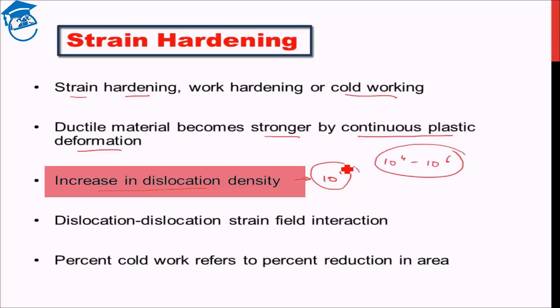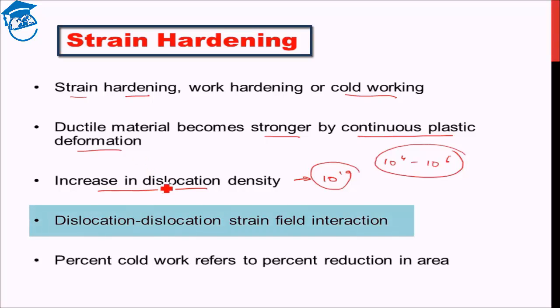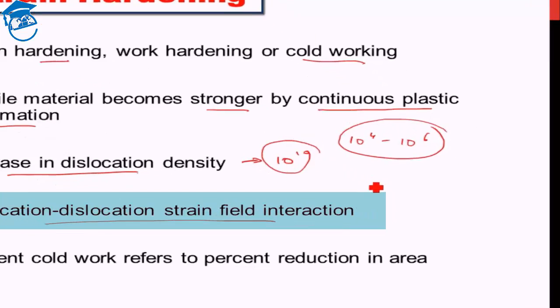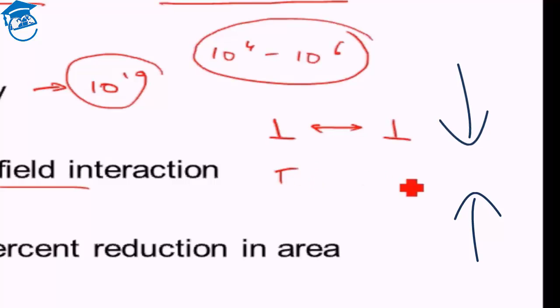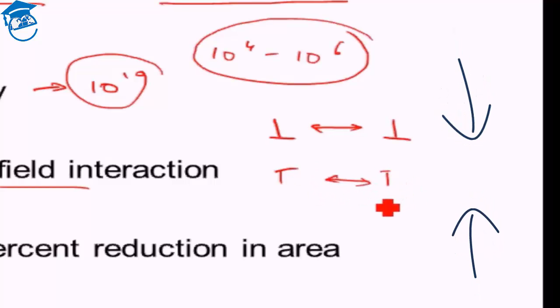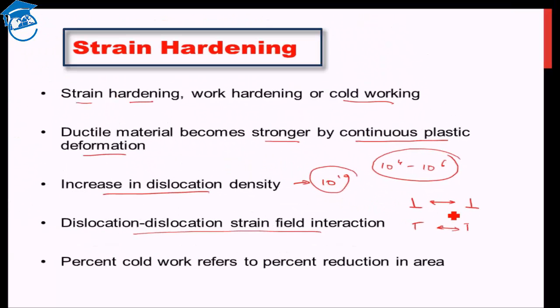So what exactly is happening: you deform a material, dislocation density starts to increase, and that starts to prevent further deformation. The deformation kind of restricts further deformation by increasing dislocation density and leading to dislocation-dislocation strain field interaction. Two dislocations of the same sign repel each other, and two dislocations of opposite sign attract and cancel. Since dislocation density is much higher there is more chance for interactions. This is the basic physics behind strain hardening.